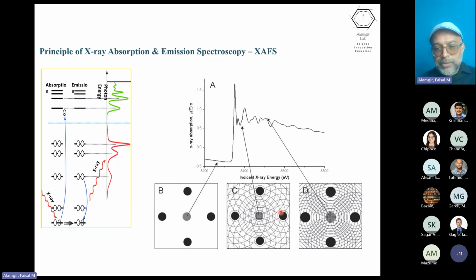But the separation between these fringes, which corresponds to the wavelength of the electron, depends on the energy of that electron. So if the electron energy is higher, the wavelengths are narrower. So here are 2 points, this point here and that point there in energy. At this point here, the free electron has more energy, therefore shorter wavelength, and you can see that the fringes are narrower. And here it has less energy, therefore larger wavelength, and so the fringes are more separated.